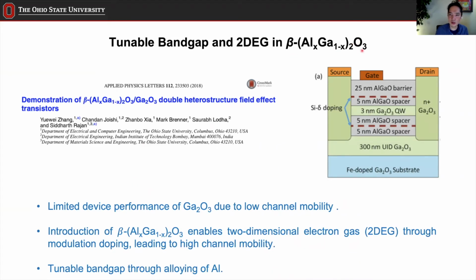This material is based on beta gallium oxide, but now aluminum atoms are involved. Basically it's an alloying between gallium oxide and aluminum oxide, or sapphire. Why are we doing this? If you know the background, I don't know much, but what I know is that gallium nitride is very popular, but the community has been trying to get aluminum involved, so you have aluminum nitride and gallium nitride mixed together. The purpose is the same here: you get the alloying of aluminum oxide and gallium oxide. Why? Because you want to form, for example, a two-dimensional electron gas at the interface that can increase the channel mobility, which is actually low if you just have the gallium oxide interface. That's one thing you can achieve.